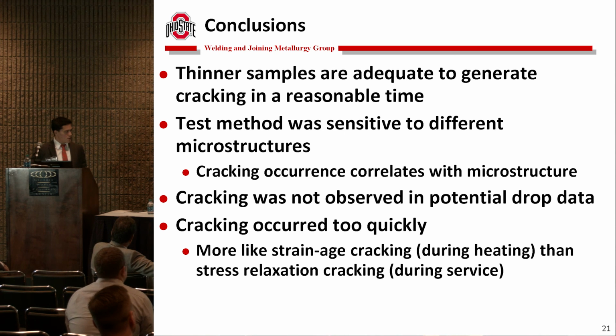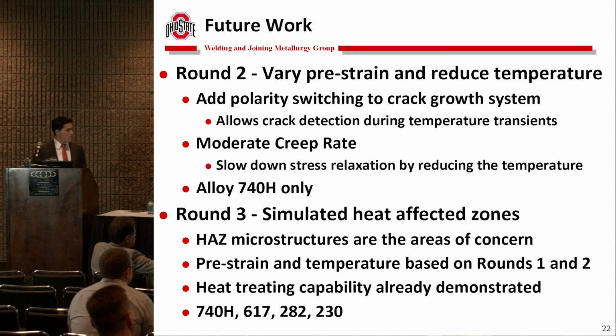Unfortunately, I didn't observe the cracking in the potential drop data, which makes me think it occurred in the first 130 hours when I was still trying to get it set up. And so in that case, cracking pretty much occurred too quickly, and it's more like an on-heating cracking mechanism, such as strain-age cracking. So in order to slow that down, I want to change the pre-strain, which I don't think will affect the rate of cracking, but reducing the temperature certainly will. In order to make sure I detect cracking early on, I'm going to add a polarity switching feature.